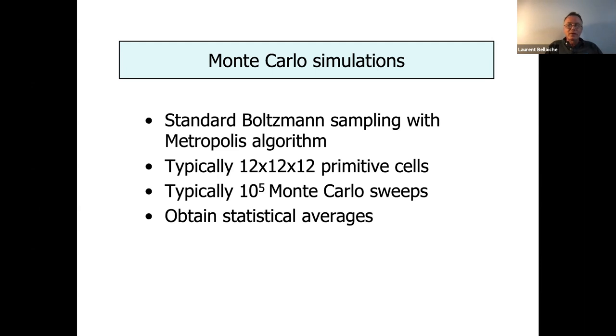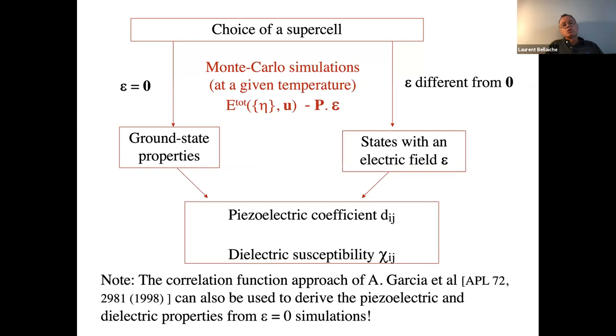This was developed by Sergei Prokhorenko. Usually, you use 100,000 Monte Carlo sweeps, but if you are dealing with very subtle things, like for example magnetism, it's much better to use 1 million Monte Carlo sweeps. And then when you get this calculation as output, you do statistical averages. For instance, this is one idea, you can choose a supercell. On the left side, you do calculation when there is no electric field, epsilon equals zero, you get the ground state properties. You can also do calculations for which you put an electric field.